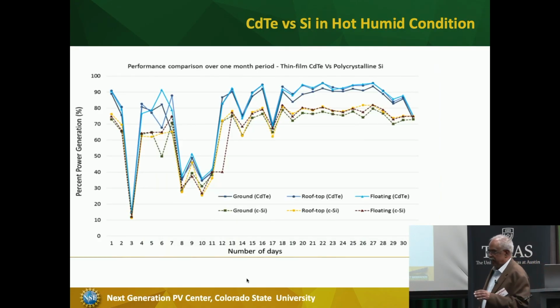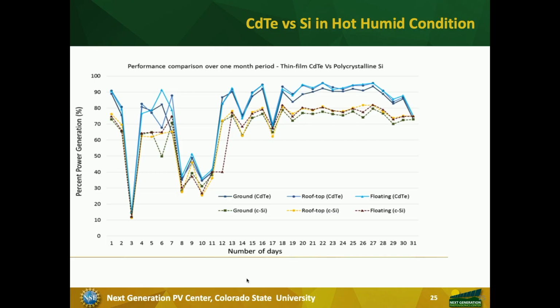And we have compared, at one point in history, a CAD telluride panel with a silicon panel. This was done in Bangkok with our collaborators from the Asian Institute of Technology. The blue curve is cadmium telluride, and the other color with the yellow and the black dots is crystalline silicon. These were all same vintage, and here was a 1 month of comparison. And you can clearly see that the CAD telluride panels produce more power than comparative product of crystalline silicon. It can be anywhere from 10% to 5% increase in power, everything else being the same. So the difference in efficiency is kind of wiped out when you look at hot, humid climates and look at the amount of power produced.